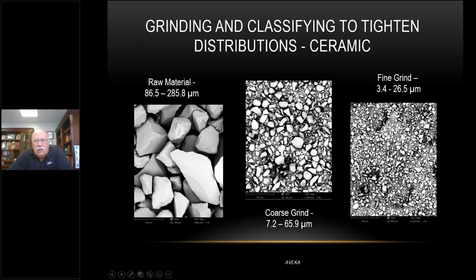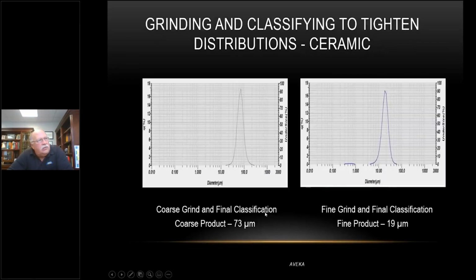So what we did is we now took these materials, each separately, the coarse grind and the fine grind, and we sent them over to our classifier, and you can see the classification is much, much tighter. We got rid of all of the fines in the coarse cut, and most of the fines in the fine cut. And we changed that average size distribution from a 34 up to a 73, and a 14 up to a 19.